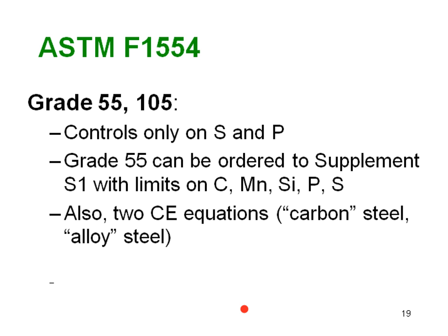Now it turns out 55 and 105 are lumped together when it comes to chemistry. And there are only controls on sulfur and phosphorus, meaning there are no controls on carbon and alloy. A grade 55 can be ordered to the optional supplement S1. And when you order grade 55 to supplement S1, limits are imposed on carbon, manganese, silicon, phosphorus, and sulfur. Additionally, there are 2 carbon equivalency equations that help limit the hardenability when you have welding involved. And again, that would be imposed only when you order to supplement S1.